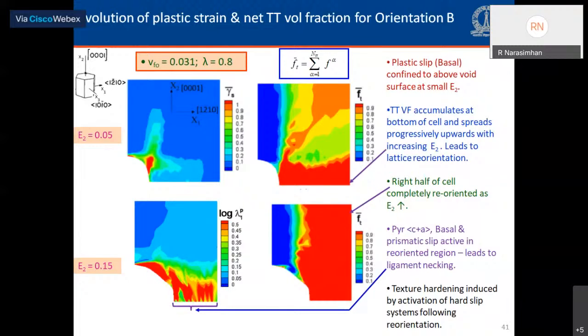Basal slip and extension twinning are active, as you can see from the top two contour plots. Basal slip emanating out from the void surface, tensile twin volume fraction contours starting from the lower corner of the cell, and as the strain increases, it engulfs a major portion of the cell, as you can see in the bottom right side image.